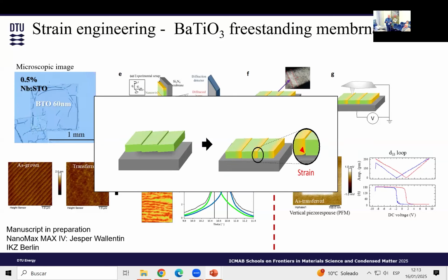To cut the story short, what we think has happened is like this. We grow the material on top of STO, SAO, and then the BTO on top of it. So we think that what happened is you get a replica, and I showed it before here. You get a replica of the terraces already on the BTO. And when you take the material and you put it on the substrate, it just relaxes. It relaxes a little bit, but there is still some residual strain in the material, and the residual strain, we think, is what brought about this modulation in the line.